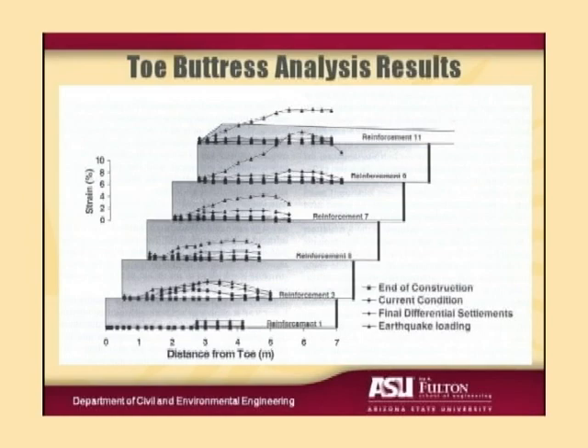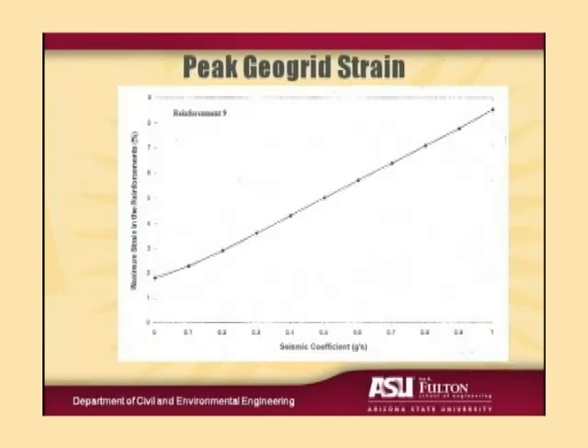And so you can see reinforcement level 9 is the critical level with an axial strain on the order of 10% in the geogrids. In fact, I think I have a slide with a seismic coefficient of 1G, which is what we used, because that's what our finite element analysis indicated. We were getting strains on the order of 9% in that geogrid. We were running the test out to 20% without rupture, so our interpretation of that was that the performance of the toe buttress was adequate, even if after 30 years of differential settlement, it got hit by that design earthquake.